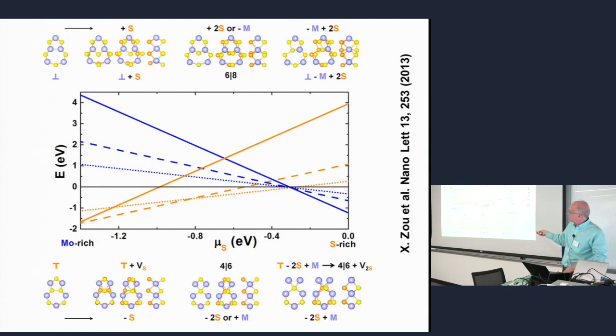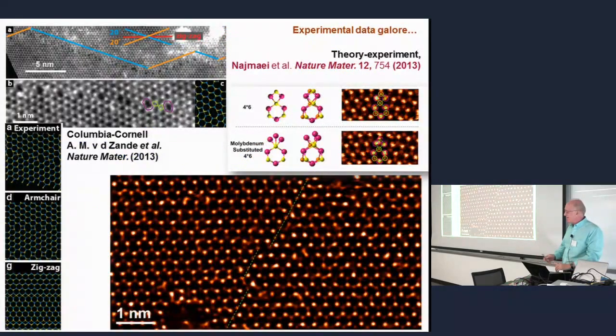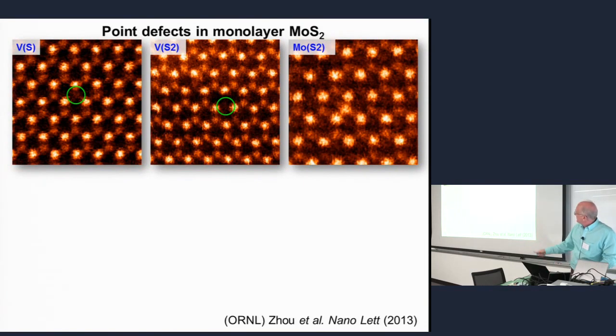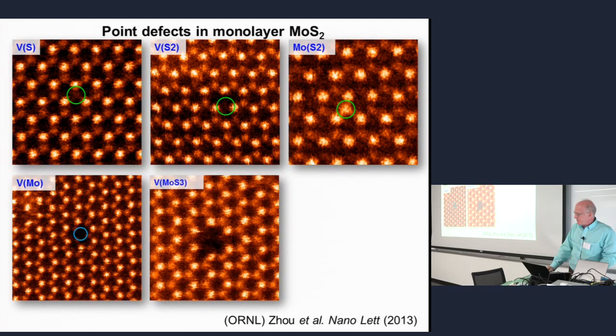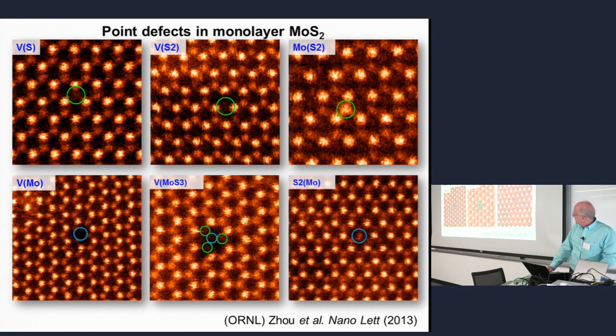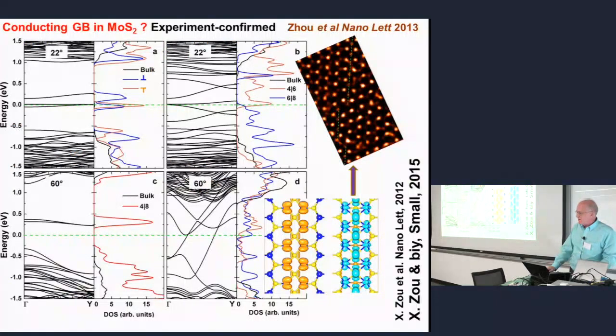You maybe need to repeat calculations if you want precise, if it's something like tungsten diselenide, but it will be exactly the same slide, just with slightly different numbers. So that's the nice thing about it, that you learn it once and then you can do it for different things. After we figured out the structures, then you know what you look for. You find them in experimental images, so this was beautifully, can be seen that all these defects can be found. And I don't discuss point defects because they're much simpler, but these are vacancies. You can identify them easier. They're not so tricky as dislocations. They're observed in experiments, and then using quantum chemistry or solid state, you can find levels and optics and so on.